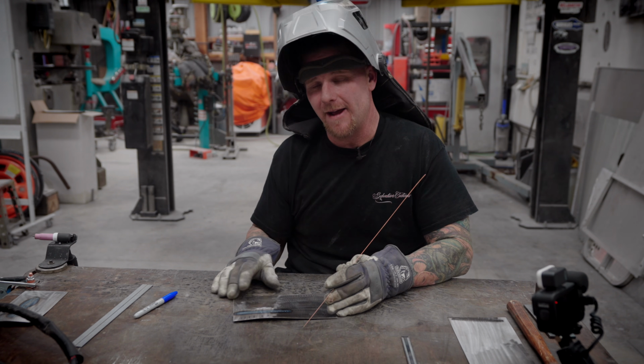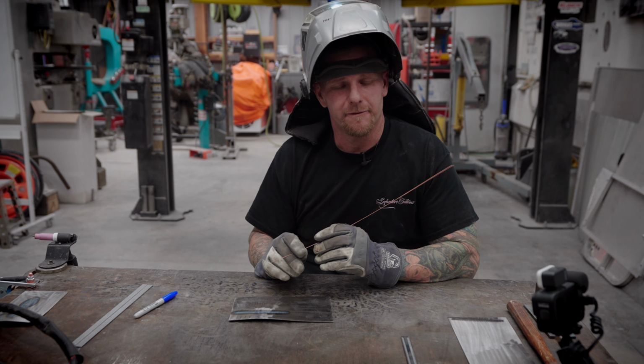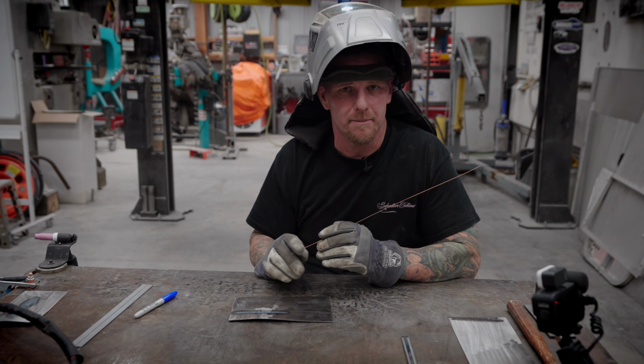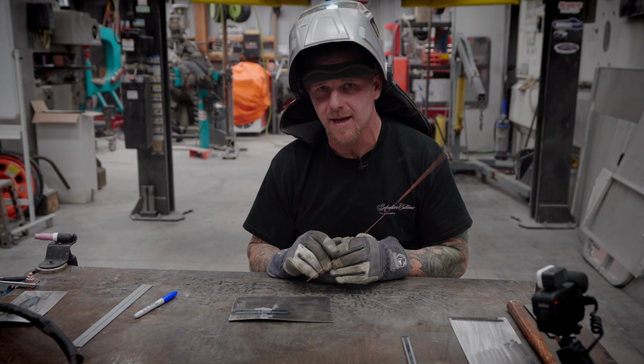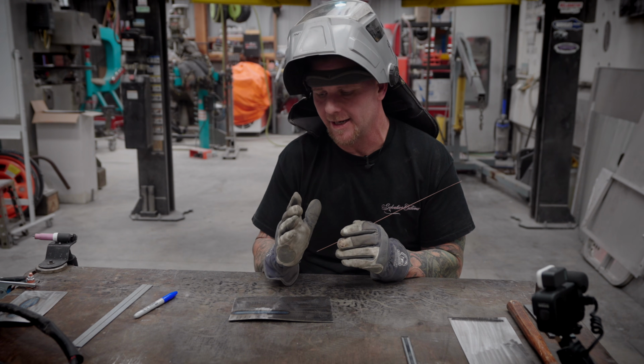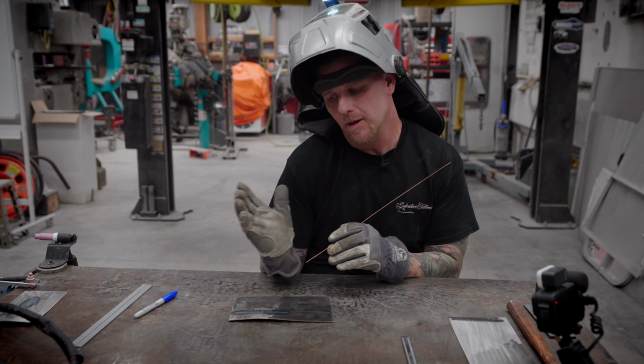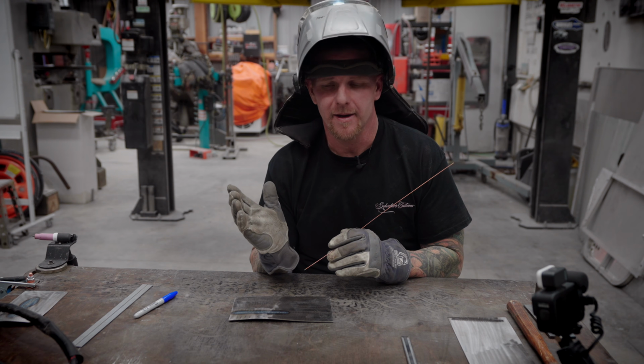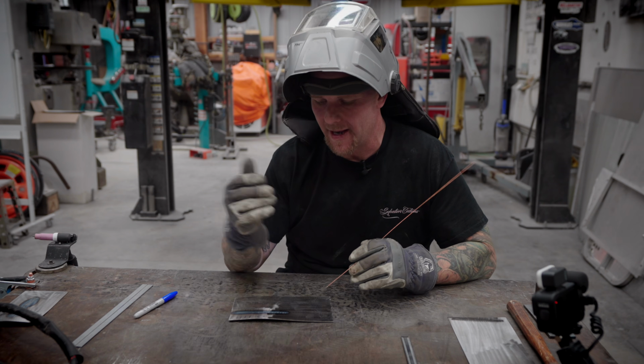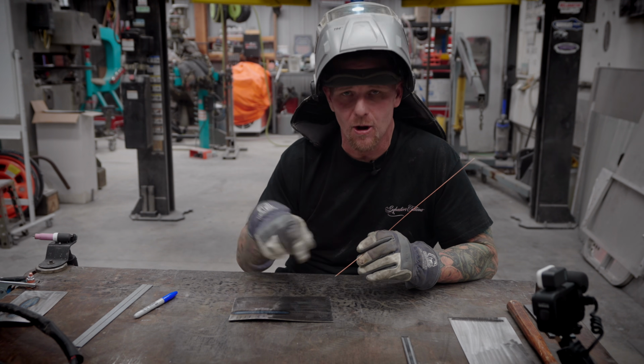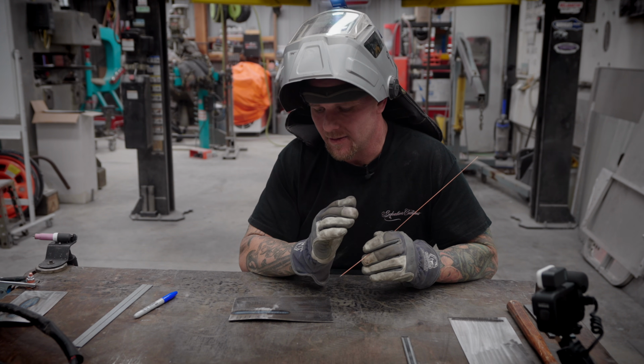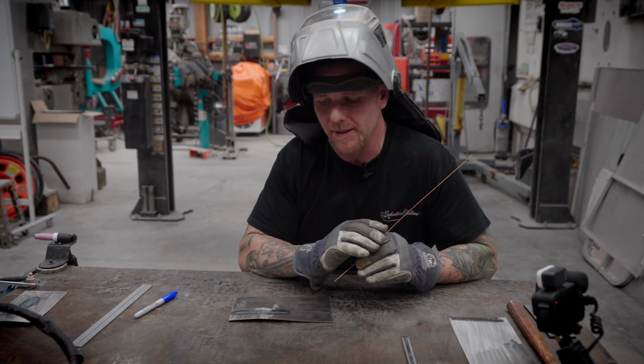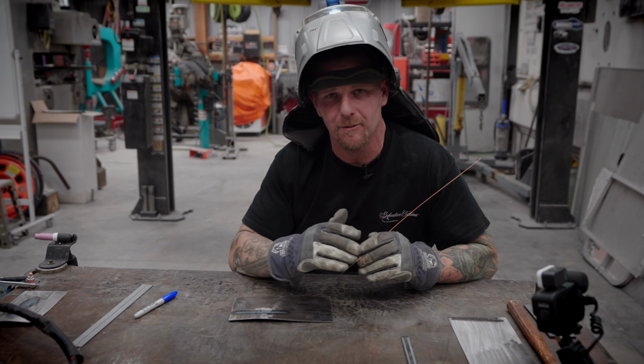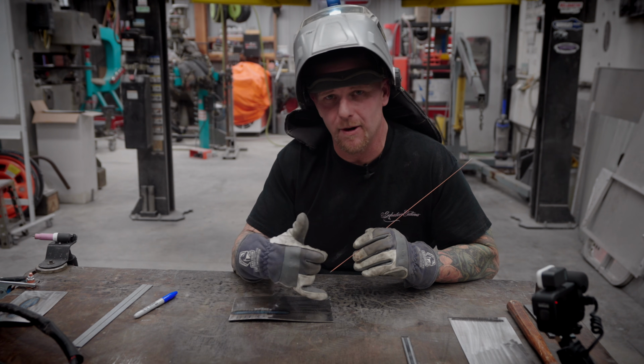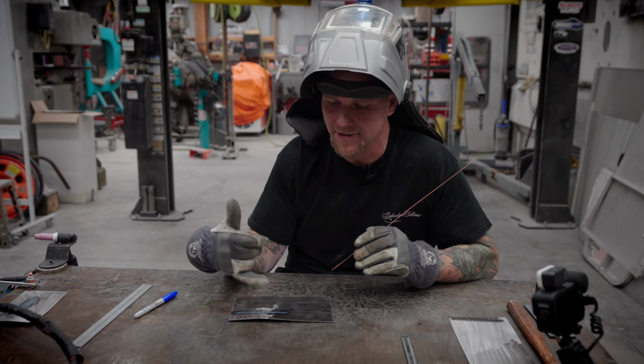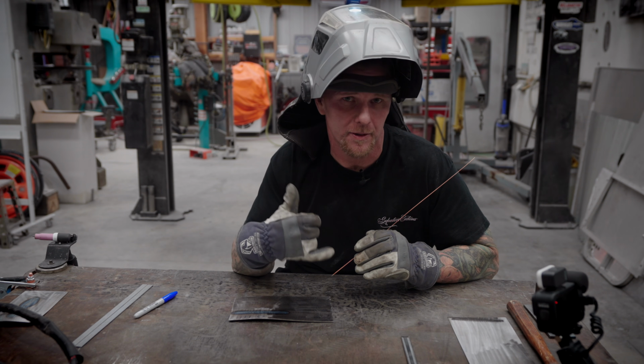There's good videos I've actually seen on YouTube. If you look up flame straightening, they use it in high-rise buildings to pull back massive I-beams, and it just gives you a really good understanding of how that heat will pull the metal in one direction or the other. And the reason that nobody likes to TIG weld sheet metal is because it just gets out of whack so fast that it's not usually obtainable, because the person that wants to try to do a nice TIG weld doesn't understand that even the perfect TIG weld gets warpage. It's understanding how to remove that warpage that's the most critical factor.